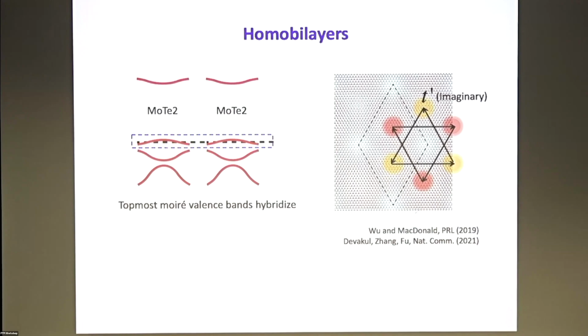You actually have to at least take into account the first two bands, they are degenerate. And in general, they can hybridize. Okay. And it turns out that both in a paper from Wu and also from Liang Fu in 2021 in a Nature Communications paper, that shows that the low energy physics of the first four bands, the two bands here, can actually be mapped in some twist angle to a Kane-Mele model.